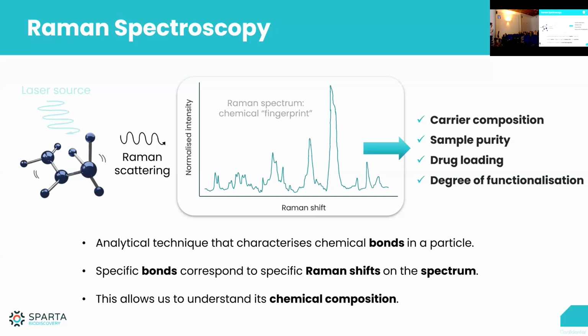What's happening is that the laser photon hits the molecular bond and transfers a small amount of its energy to the molecular bond, and it leaves the particle with slightly less energy. The amount of energy that it has lost is indicative of which molecular bond it interacted with. So what we get out is a spectrum. We use a very sensitive spectrograph and a camera for Raman spectroscopy to measure all these different energy losses. You can see here that the intercept would be 0, which is the light that didn't lose any energy, i.e. the same wavelength as the laser. That's not interesting. We block that light. Then all the light that comes off from these different peaks is more and more energy lost from the photon, from different molecular bonds it interacted with. It's very well characterized at which positions certain molecular bonds interact with the light, which means that we can get the compositional profile, or a compositional fingerprint, of the nanoparticle that we're looking at.